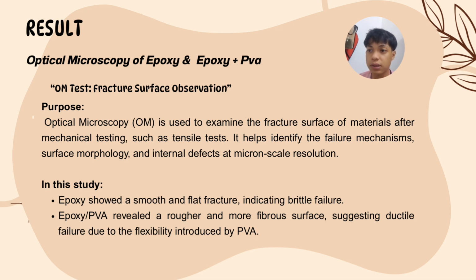This means the material broke suddenly without much plastic deformation. On the other hand, the epoxy plus PVA sample had a rough and more fibrous surface, indicating ductile failure. This shows that the addition of PVA improved flexibility, allowing the material to stretch and deform more before breaking. So the optical microscopy helped confirm the mechanical behavior seen in the tensile test. Epoxy is brittle, while epoxy plus PVA is more ductile and suitable for applications that require flexibility.